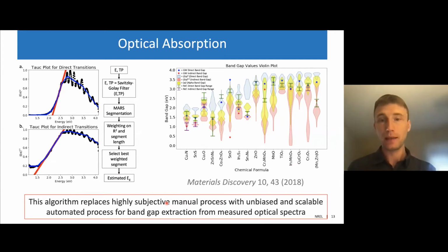So this is often done by Tauc plots, and we have benchmarked several different ways in constructing, in processing the data to make these Tauc plots, as well as then extract the bandgap out of these Tauc plots and benchmark them against the theoretical GW calculation that exists in NREL HTEM-DB.